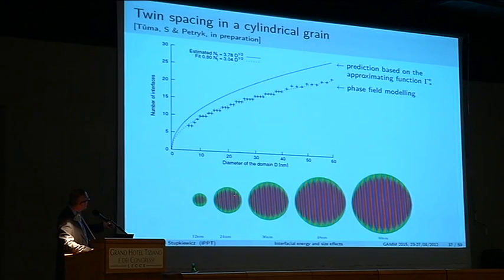Another issue is that if you look closely, the thickness is not uniform, while our predictions assume that the laminate has a constant spacing. So this is another difference between the two. Finally, there are local effects. We have assumed that the interface is perfectly planar, while in practice, material can modify slightly the shapes so that the energy is lower at the end.